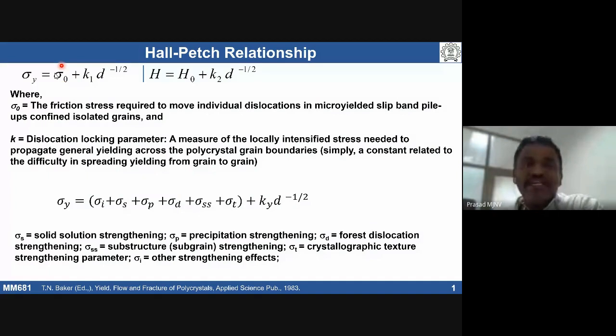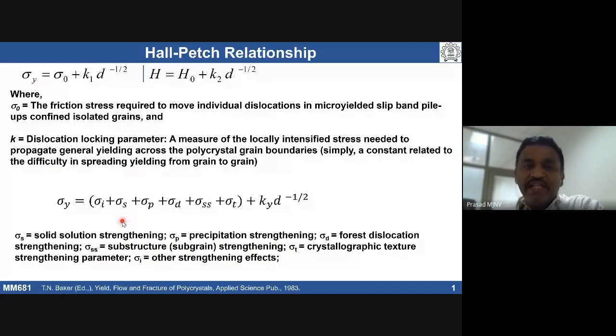Sigma naught basically considers the friction stress required to move individual dislocations from micro-yielding slip bands. This friction stress comes as a function of several components depending on the alloy, the amount of deformation taking place, and the polycrystallinity in terms of crystallographic nature and texture. Peierls-Nabarro stress, solid solution strengthening, particle strengthening, dislocation-based strengthening, and substructure formation within a grain, such as subgrains, can also contribute. If the metal has texture, there is also a texture effect. All these things are part of sigma naught.